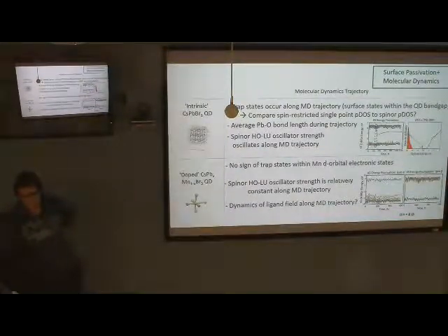You can just look at these oscillations and do the Fourier transform. Actually, I think he was doing the autocorrelation function first, and then making a Fourier transform from the autocorrelation function, to get the spectra, which gives you some kind of frequencies, right? Which would correspond to the normal modes, either acoustic or optical modes, right? Collective motion, which will be really related to this lead oscillation. And you can probably find in the literature these lead-oxygen normal modes for the surfaces.